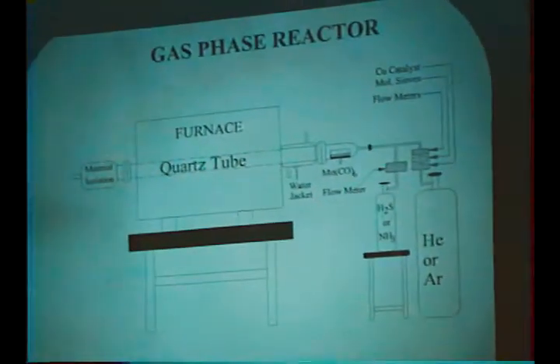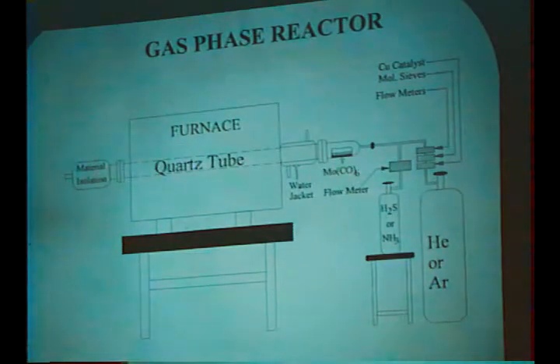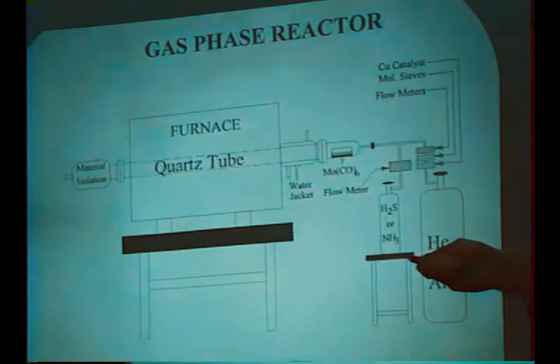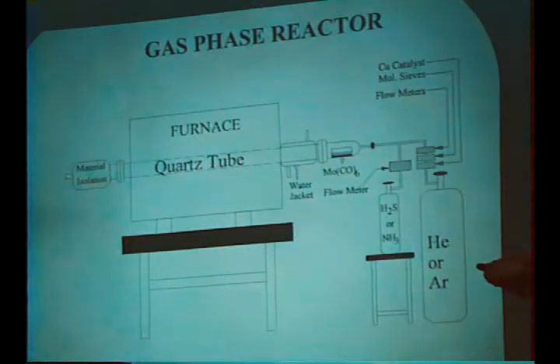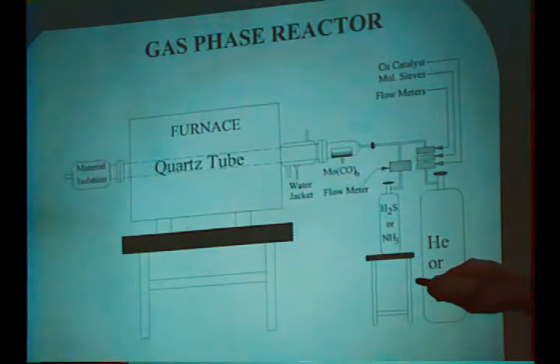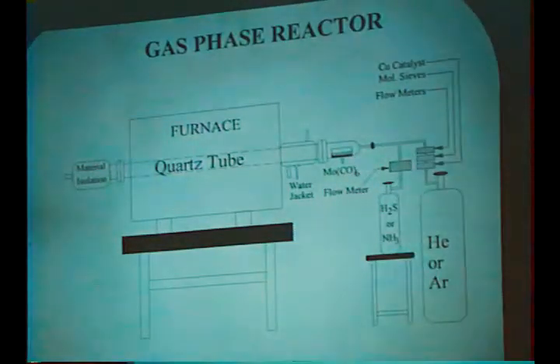Now let me make a note at this point. The materials that are made with this reactor are very, very fine particles. In fact, the particle size is around the nanometer range, but the materials are collected using standard filter paper. If you can imagine a vacuum cleaner, you have an idea of what we're using to collect these materials. Fortunately, nature is on our side. The materials agglomerate electrostatically, creating big enough particles to be caught in this filter paper. Therefore, we're able to isolate the materials very effectively. Critical variables here are the gas flow rates, the temperature that we heat the molybdenum carbonyl at, and the furnace temperature. And I want to look at each of those variables and how it affects the material.